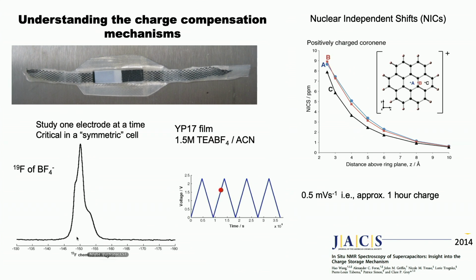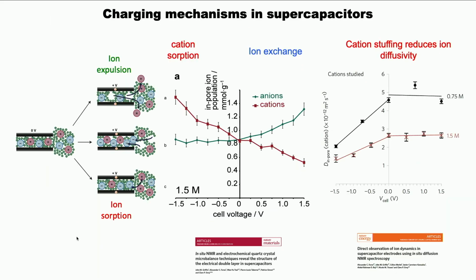And what is happening there is you're getting a reduction of the aromaticity, you have a reduction of the local field on top of it, the reduction of the so-called nuclear independent chemical shift that you're seeing there. So you're actually able to track the extent of hole doping in these carbons and say something about the mechanisms of intercalation. But that was nice from a theoretical perspective, but this method actually allowed us to ask a very simple question that hadn't been shown experimentally before.